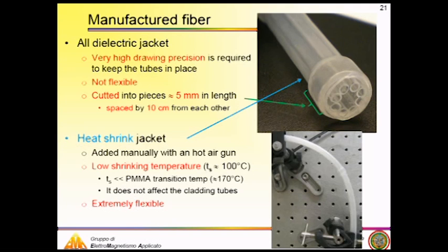The remaining part of the jacket was substituted with a heat shrink tube. This has been added manually, and the interesting part is that the heat shrink tube has a shrinking temperature which is much lower than the transition temperature of the PMMA, so we are not changing or perturbing the shape of the cladding tubes. And this, as you can see from this picture, allows us to obtain also a very flexible waveguide.